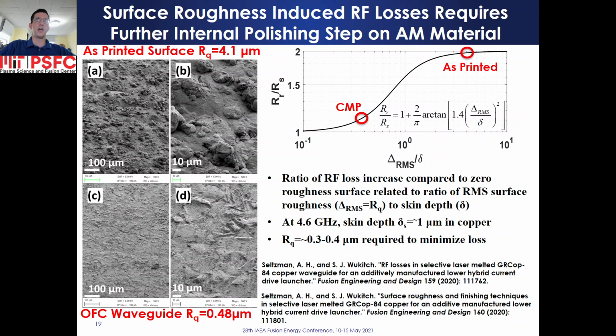to achieve lowest loss. As printed surfaces have an RMS roughness of approximately 4.1 microns, shown in SEM images on the top. For comparison, extruded oxygen-free copper waveguide has a typical internal RMS roughness of 0.48 microns, shown in SEM images on the bottom. Further polishing is therefore required to reduce the as-printed roughness circled on the plot to achieve low loss. A technique called chemical mechanical polishing is utilized to achieve the required surface roughness.